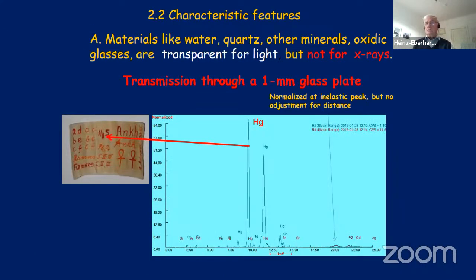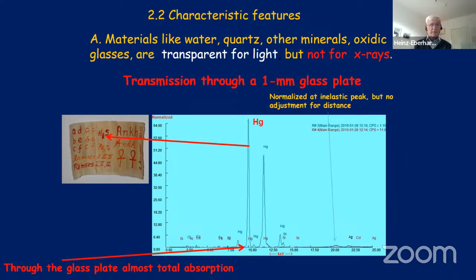But there are two features which should be kept in mind, especially for the younger researchers, graduate students, or whatever. For example, what is transmission? When you compare it with standard visible light, we all know that light can go easily through water, through quartz, through glass. But if we apply, for example, a 1 millimeter glass plate to an X-ray beam, it's completely absorbed. That is illustrated here with the mercury fluorescence L lines coming out, but with the glass plate, it's totally absorbed.